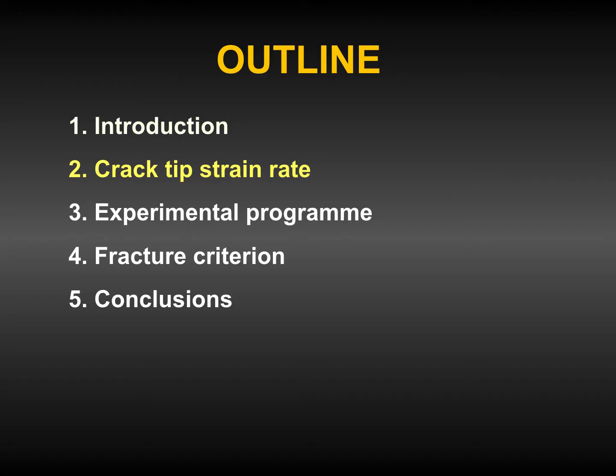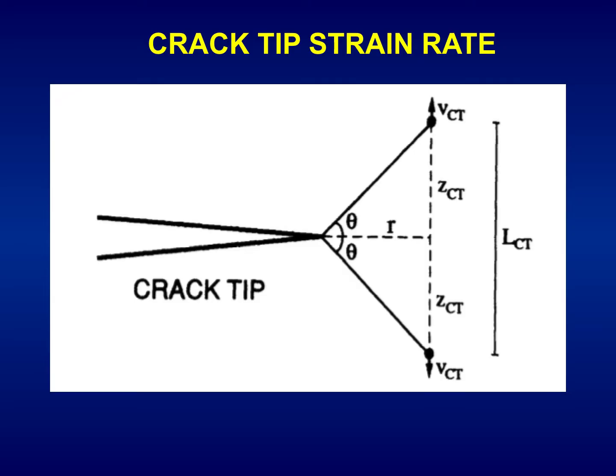Second, the concept of crack tip strain rate. This is the schematic of the crack tip. In this paper, the traditional solution in linear elastic fracture mechanics is used. Here we have the polar length R, the polar angle theta, and the vertical coordinate Z_CT, the vertical displacement V_CT, and the local reference length L_CT, the crack tip length.